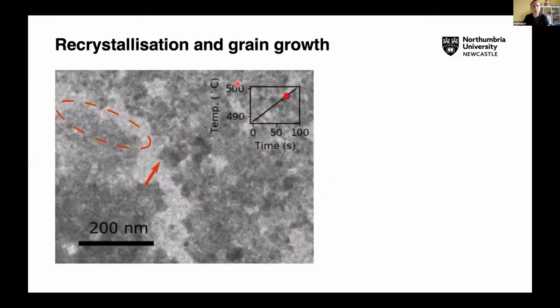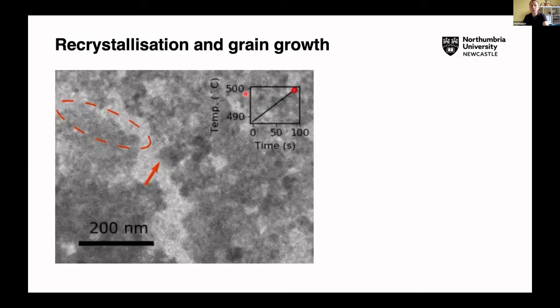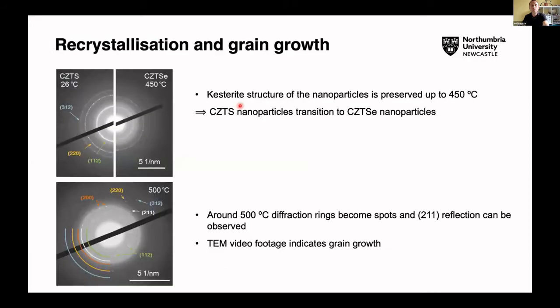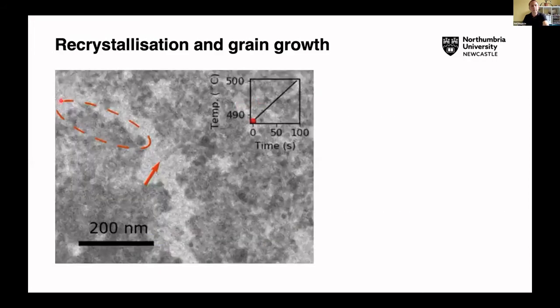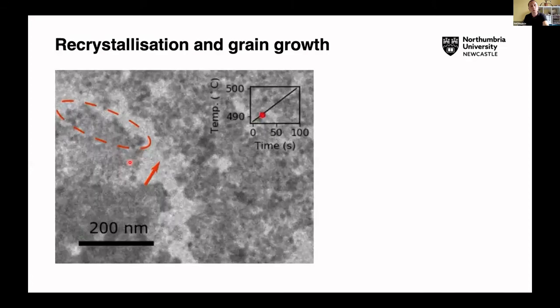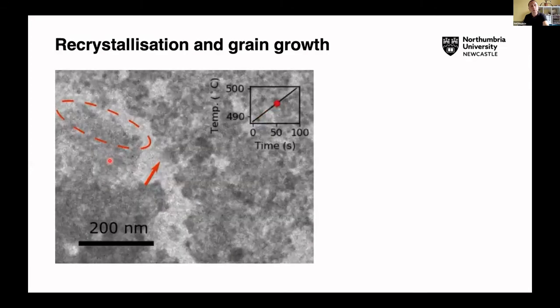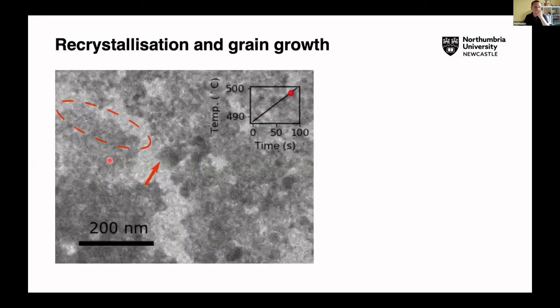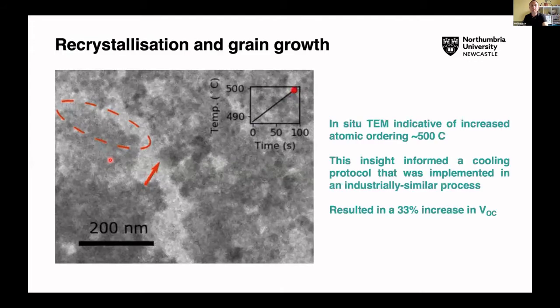So there's the evolution of that grain just growing from the nanoparticles. And interestingly, if you watch inside this dashed oval area as well, you see sort of consumption, if you like, of these nanoparticles while this grain grows. So you kind of see that area getting reduced there. So it's a kind of Ostwald ripening type process.